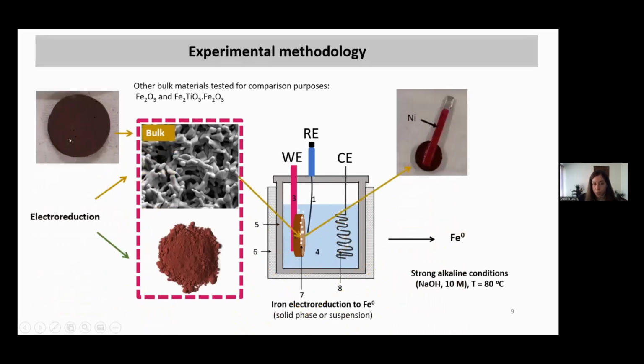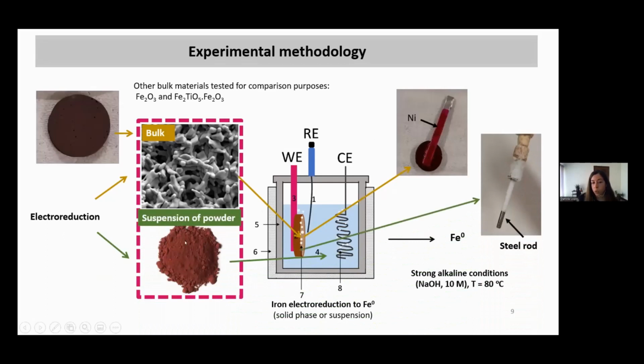So in bulk, we have this pellet that was glued with silver paste to a nickel plate, and this nickel plate is going to act as current collector, and it was painted with lacquer. For suspensions, we use this pseudobrookite powder mixed with sodium hydroxide electrolyte, and we use a steel rod with 1 square centimeter of area, and the iron is deposited in this area. And this is exactly where iron is reduced in both cases. So we use sodium hydroxide, 10 molar, and 80 Celsius degrees.